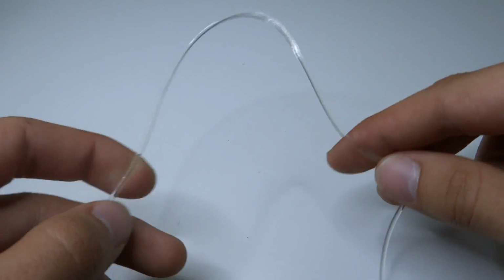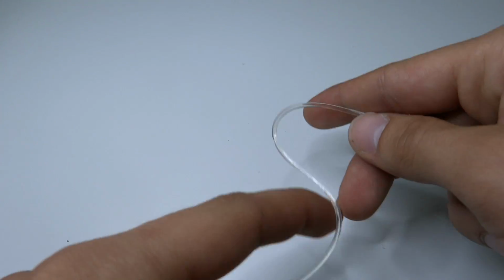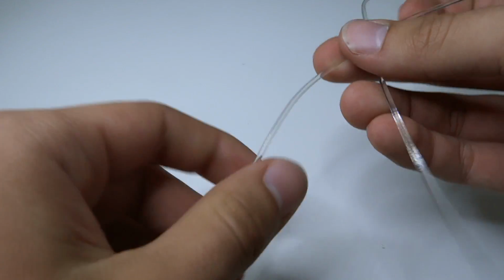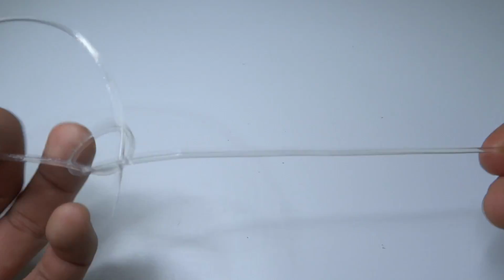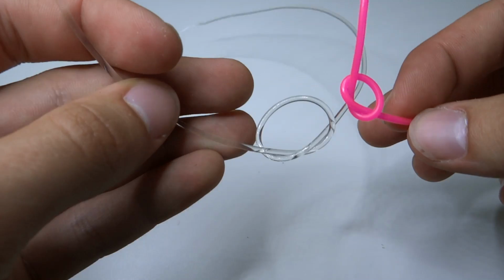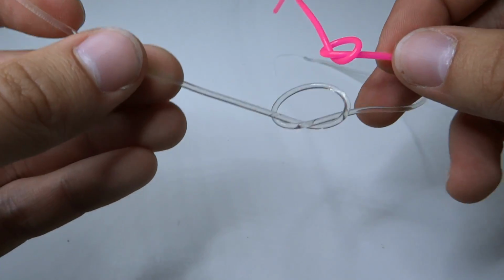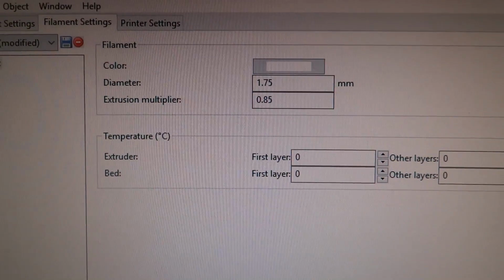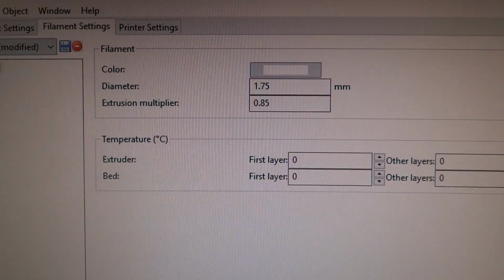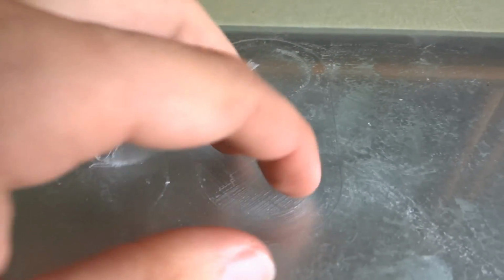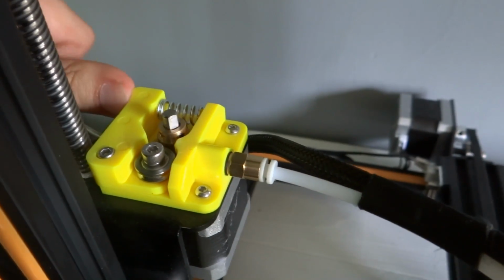That's TPU from Devil Design. It's harder than pink one and has better color. Now we should be able to print with this because it's not pink. I change extrusion multiplier to 0.85. First try failed. Reason? Filament jump in the extruder as before.